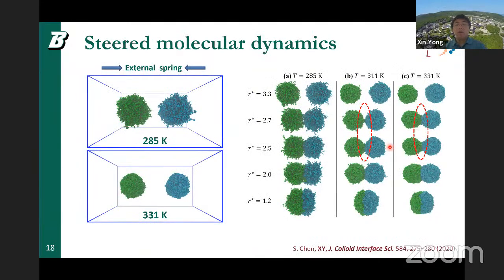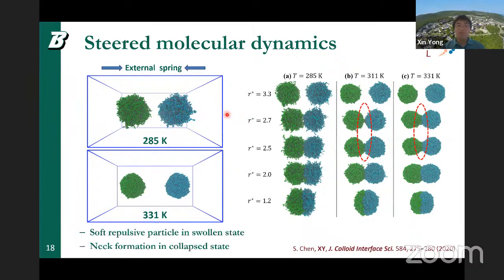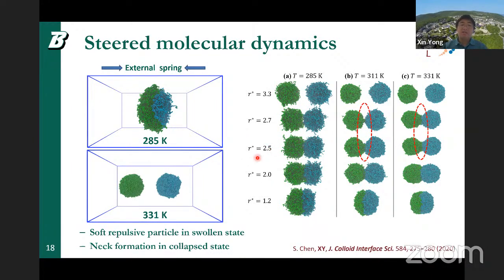And then once we have these particles or this microgel, we start to quantify and characterize their interaction. We use steered MD simulations to let them interact with each other. So basically, the steered MD concept is very simple. We add an external spring to the center of mass of two microgels, and we pull them together. The reason for doing this is that it will facilitate their interaction, and it will also provide ways to quantify their energy, as we're going to demonstrate in a minute.